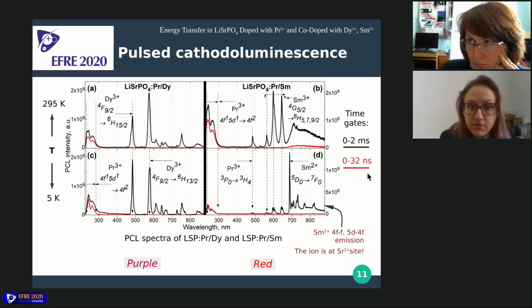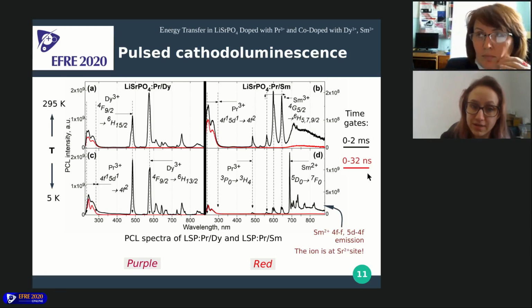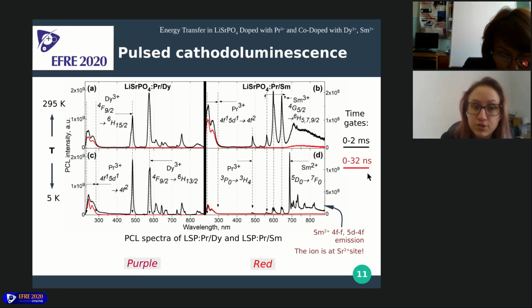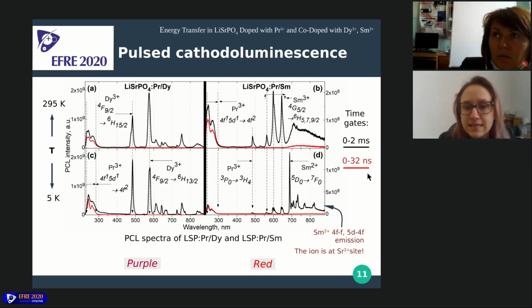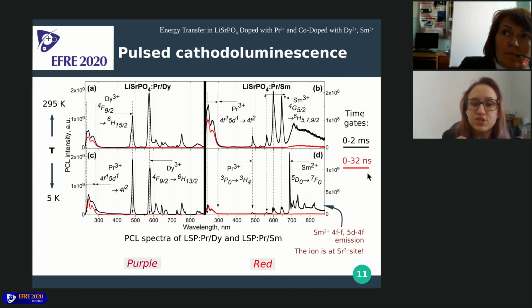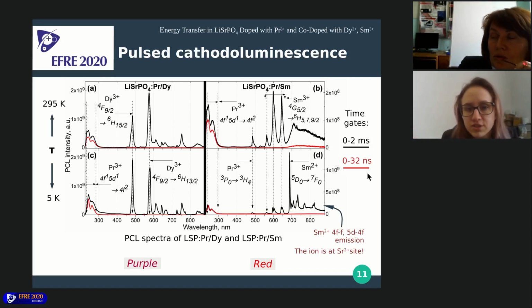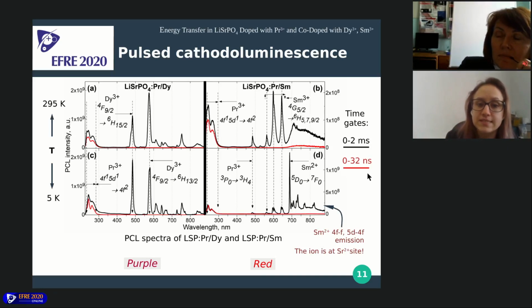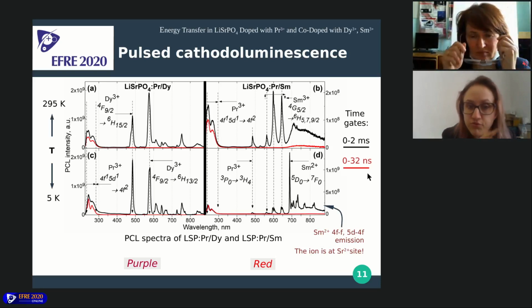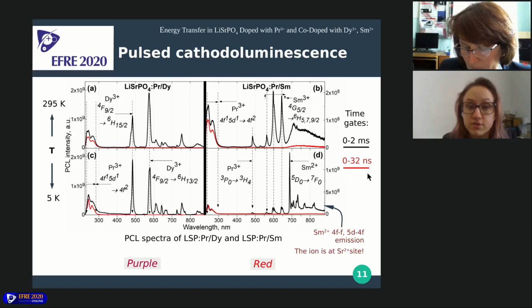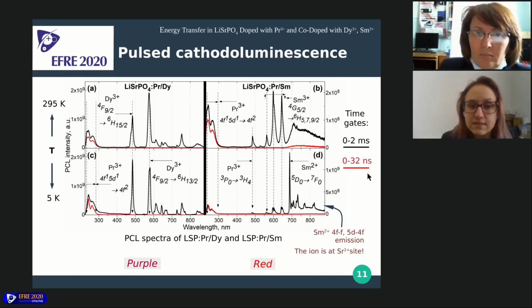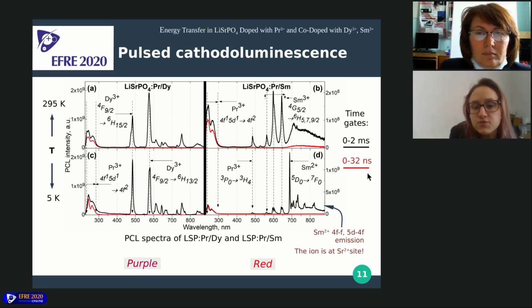For example, we have not just trivalent samarium spectral lines, which are also expected in the red region, but also there is some emission of divalent samarium ions, which is closer to the infrared region. And also there is emission that can be assigned to divalent samarium 2+, including fast transitions from 5D levels to 4F levels. It is fast. And this is interesting because it proves the assumption that rare earth ions stand on the strontium 2+ site in the crystalline lattice.